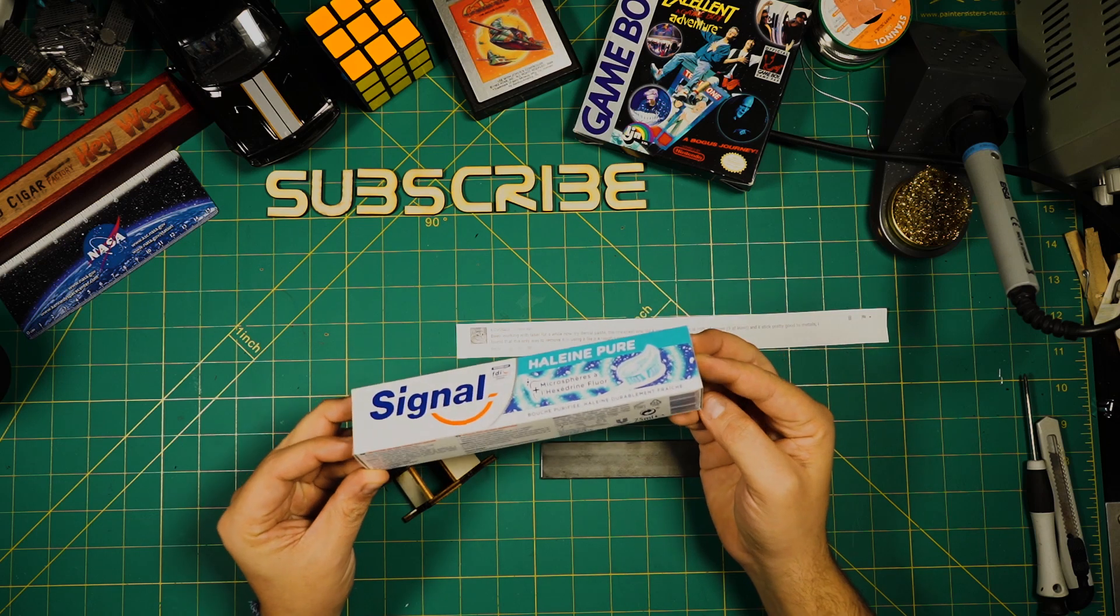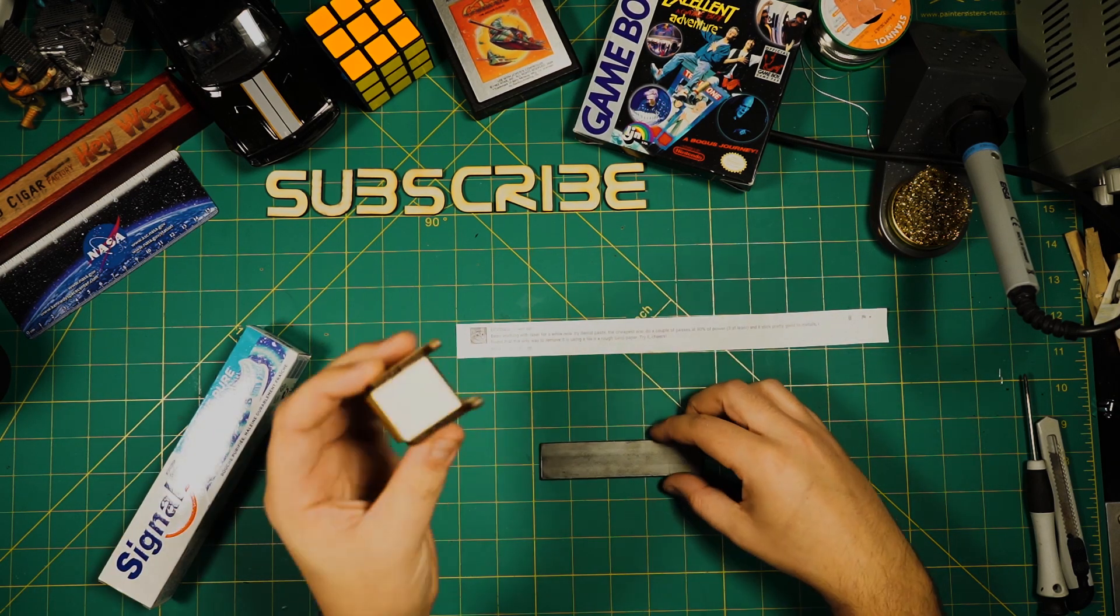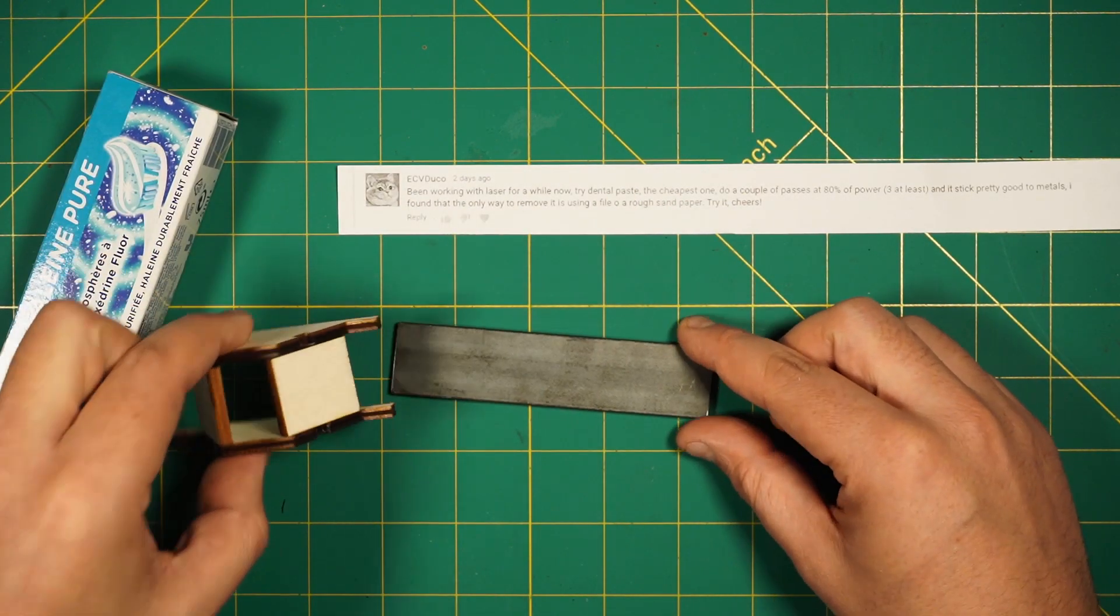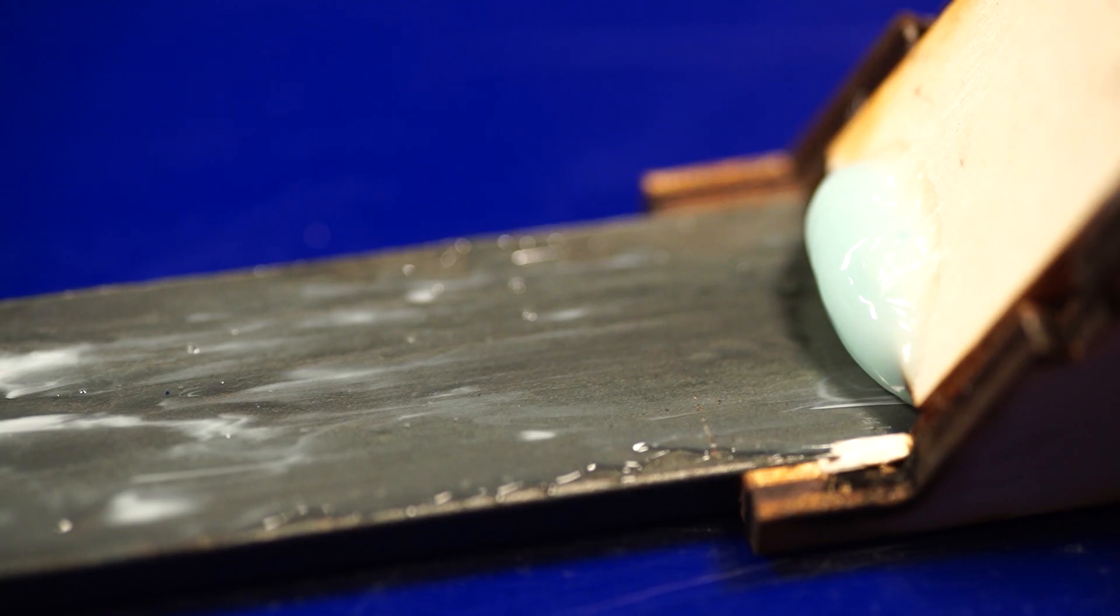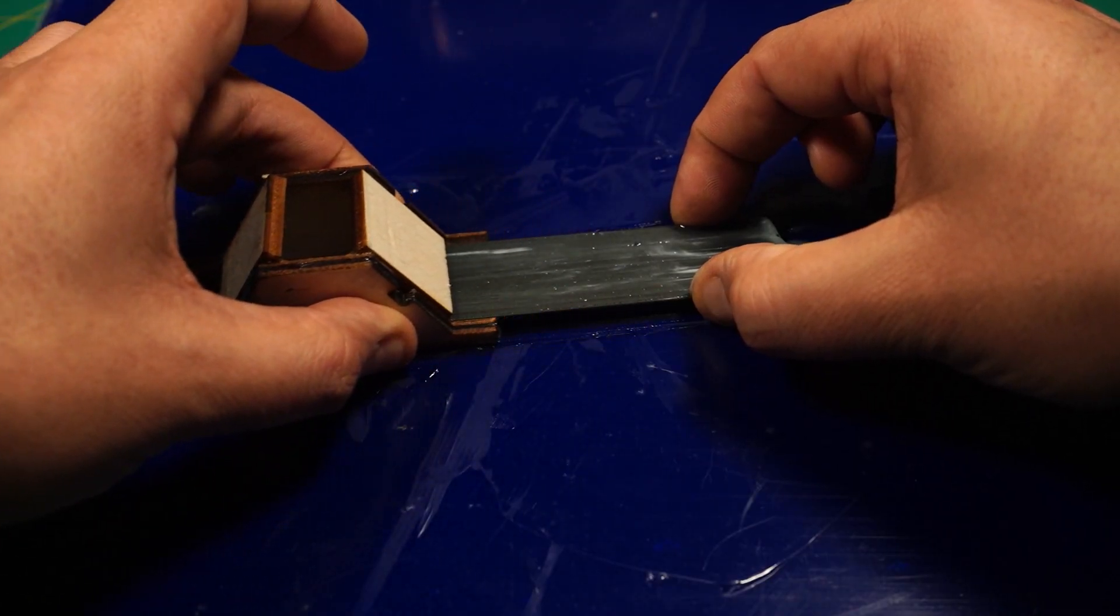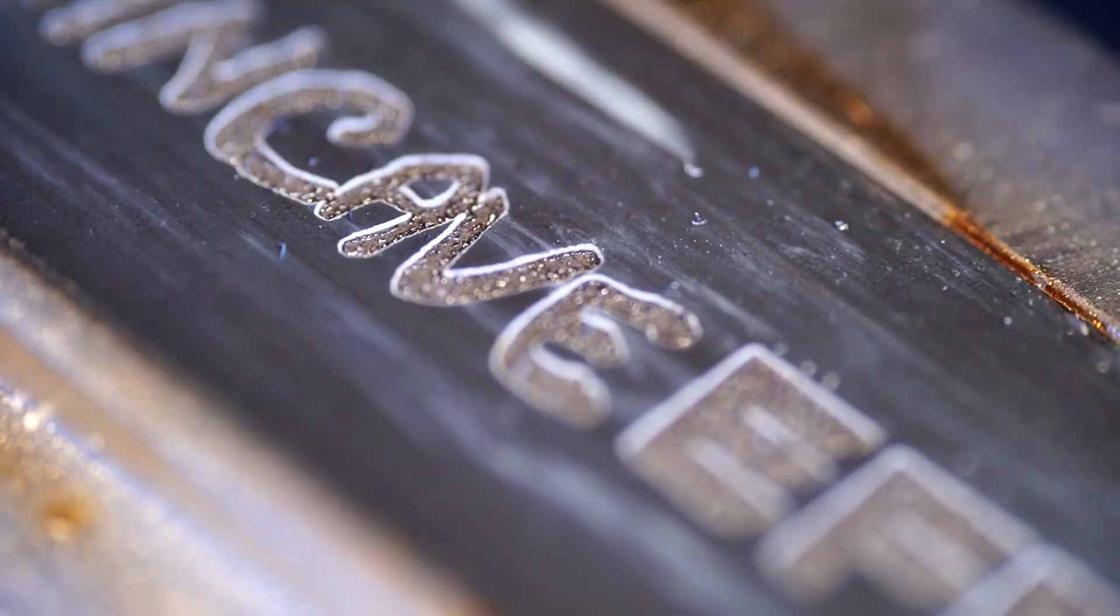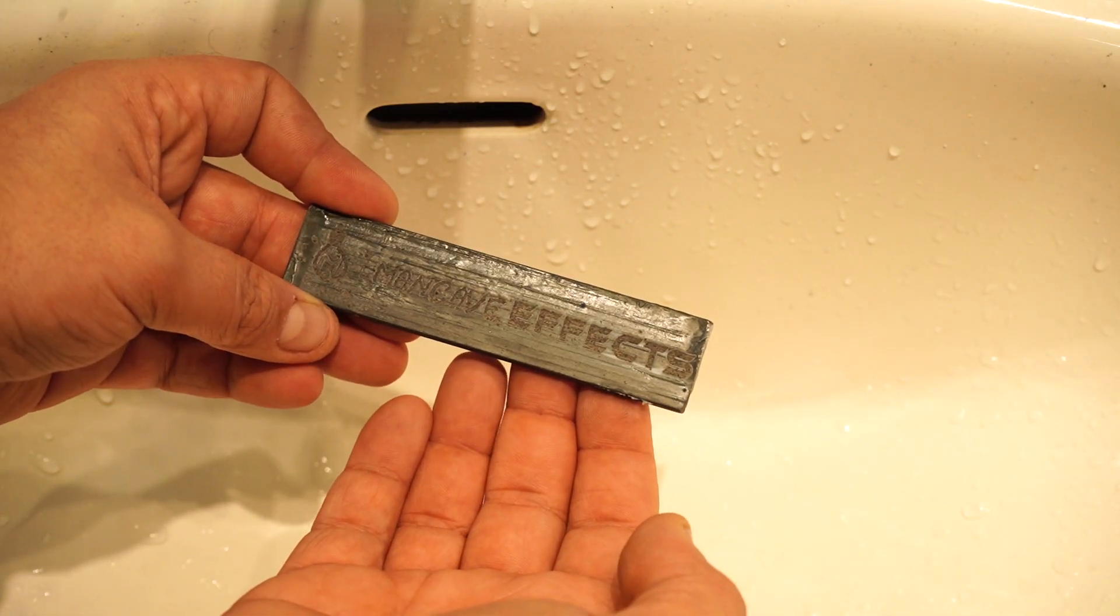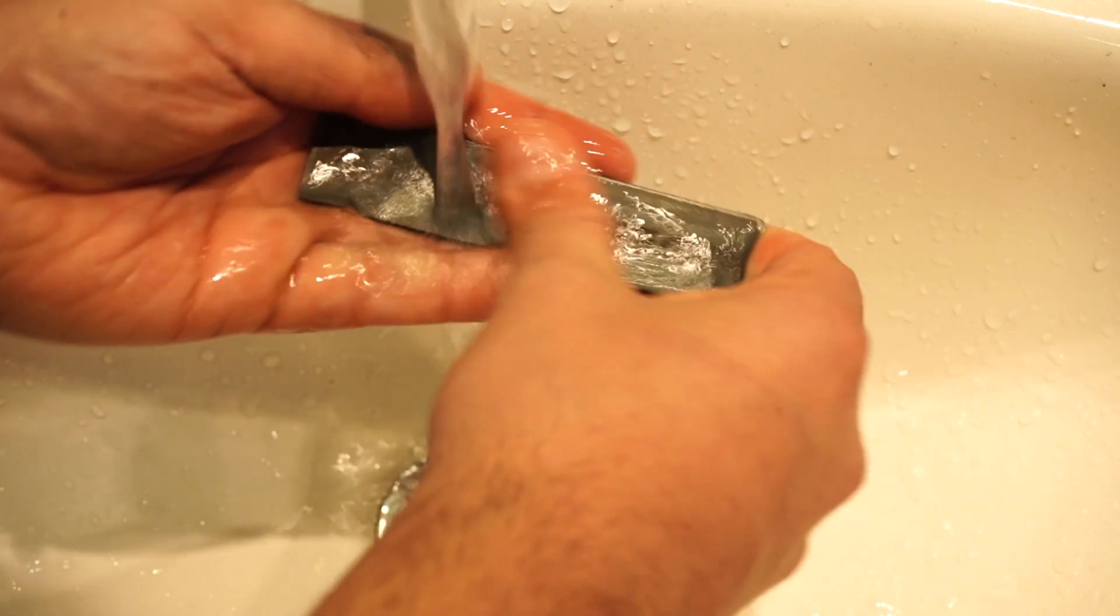I made myself a toothpaste applicator for spreading it evenly all through this piece of steel. I will layer on a 0.2mm coat of toothpaste before engraving it in 3 passes with about 80% of laser power. Now, does the toothpaste have the magical ingredient to mark metal? Let's see.